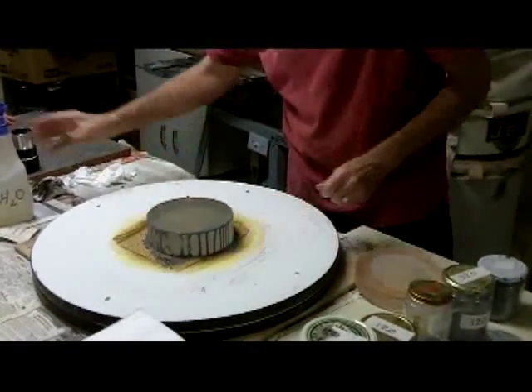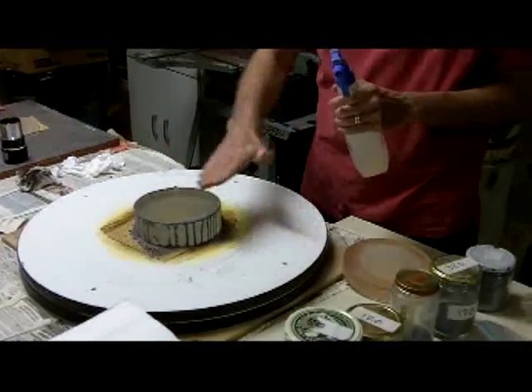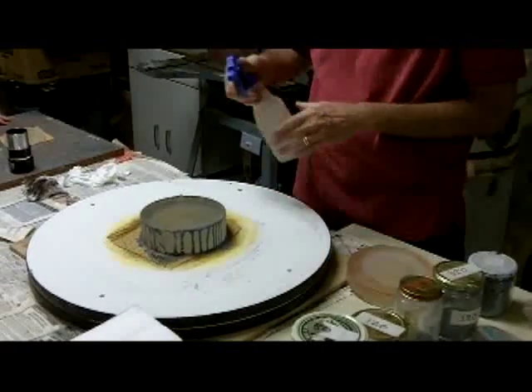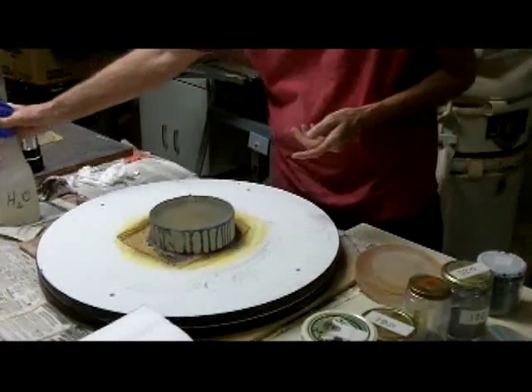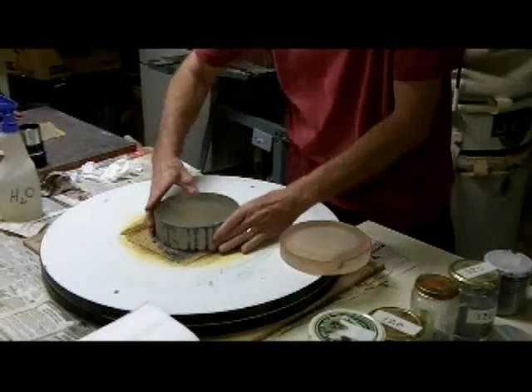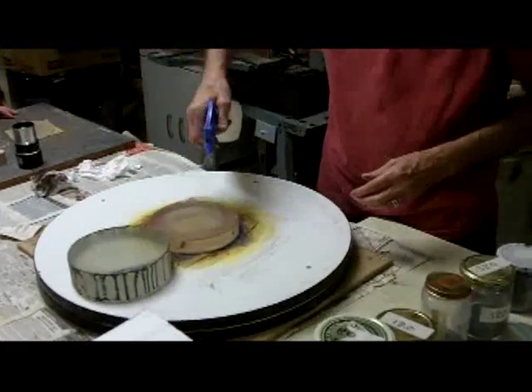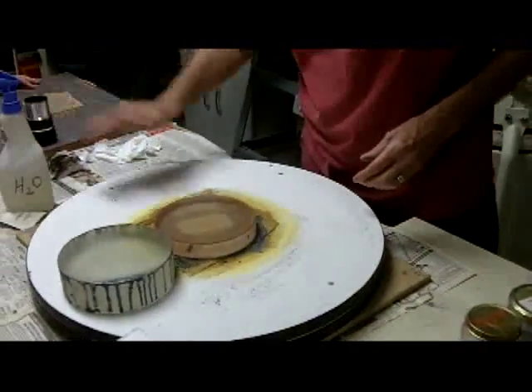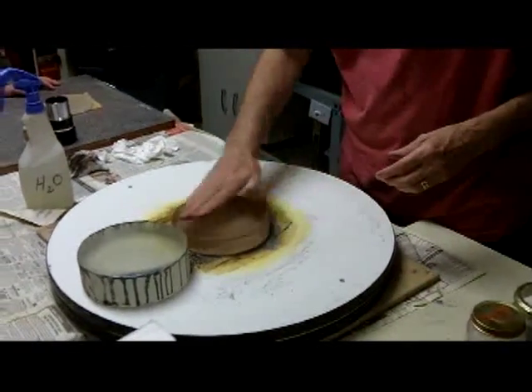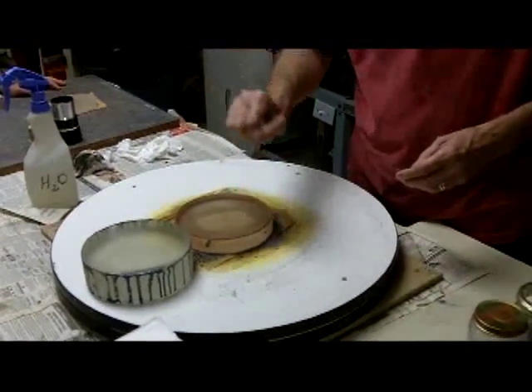So we're going to say, okay, now we've got this thing hollowed out, we've taken it out in the sun, we've looked at it, and it's at about an F7, which is going to be fine. So that should be the tool. That's the tool. I'm sorry, I've got them backwards now, because we want to turn these around. Let's start now with the mirror on the bottom and the tool on top. And you can tell that's at an F7 by the size of that curvature. Guesstimation. Given another couple of hours of work, it would be F7.